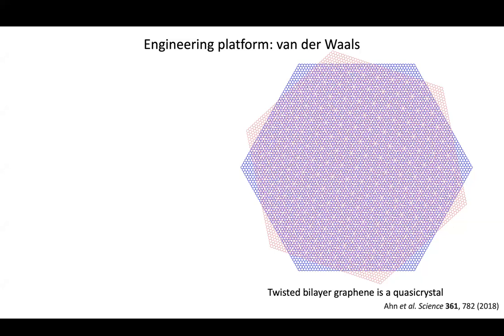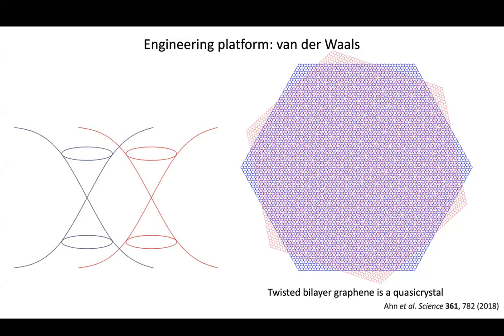Not just that the rank is larger, but actually a dodecagonal one. And this was demonstrated nicely by a Korean collaboration. However, the electrons in a transport experiment have no idea that this is a dodecagonal quasicrystal because all of the effects occur at super high energies. You measure this thing and you would not know that this is a quasicrystal. There's no manifestation whatsoever. In fact, these two layers are pretty much completely decoupled at experimentally accessible energy ranges in transport experiments. You can look at it with a TEM and you see that it's a quasicrystal, but that's it.